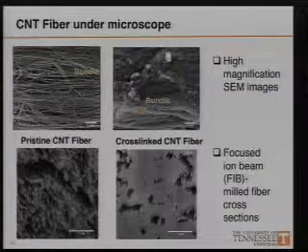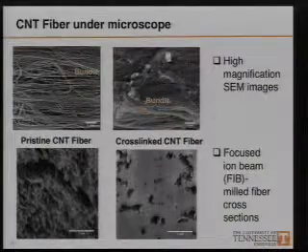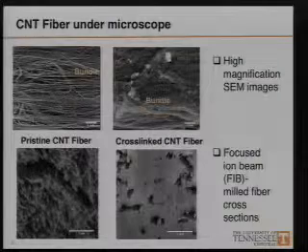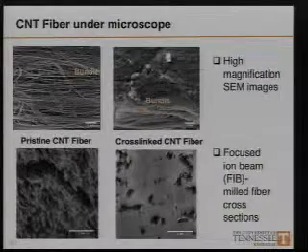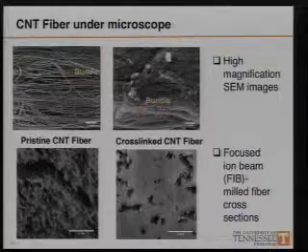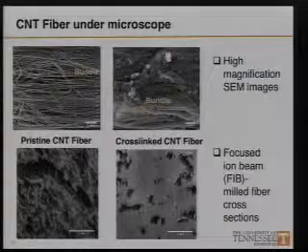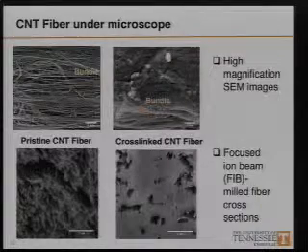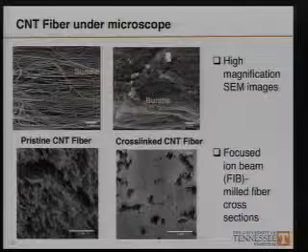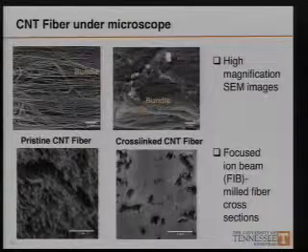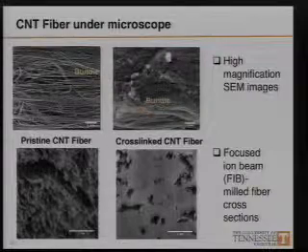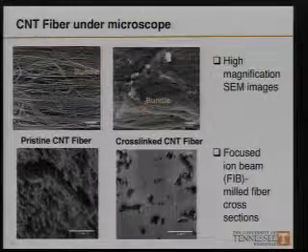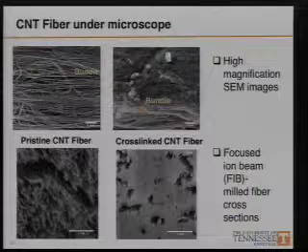Higher magnification SEM images give information on the alignment. The nanotubes are almost all aligned with slight entanglements in between, and the void spaces are observable in between the nanotubes, which agrees with the loosely packed structure in low magnification SEM images. After the cross-linking process, you'll see that the bundle size of the carbon nanotubes has increased, and it has been covered by an almost continuous polymer layer, and polymer particles are also observable.